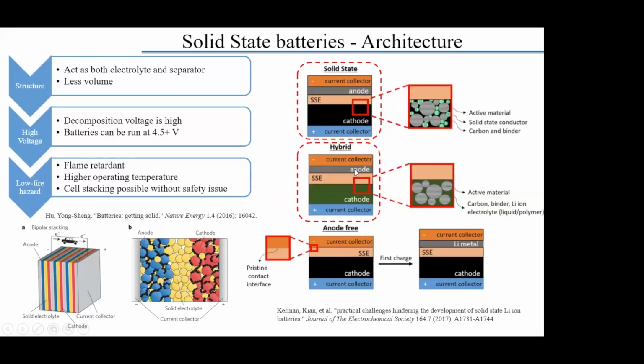The hybrid will have, basically, some of the graphitic anode retained, with a transition metal, LMO with an NCA or an NMC cathode, and you have solid state. It's kind of a mixture, right? And then there's something called anode free. Basically, there's no anode in the beginning, but on the first charge, the lithium goes from the cathode and forms lithium metal on the other side. So these are three architectures that most of the hot solid state batteries fall into.